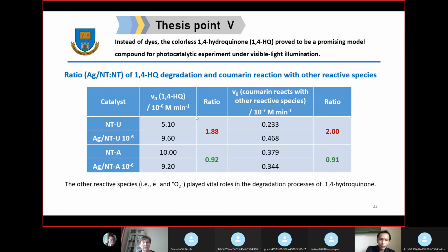If we compare the ratio of the hydroquinone degradation to the coumarin reaction with other species, we clearly see that the ratio for both N-TiO2 catalysts is similar. It means that other active species play a crucial role in the degradation process of hydroquinone instead of the hydroxyl radical.